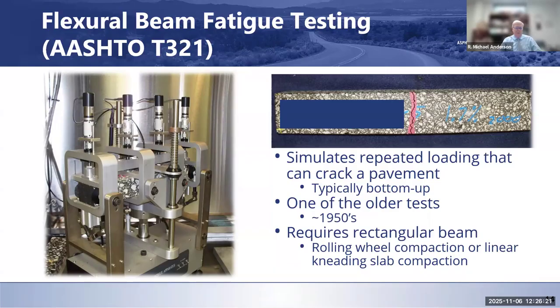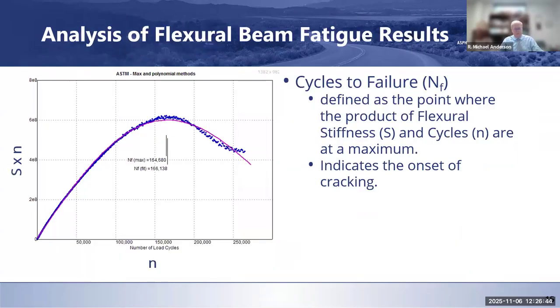So you can see what the beam looks like after it cracks. You develop micro cracks and then ultimately cracks that occur in the specimen. We've just used a red paint pen to highlight what that looks like within the specimen itself. It does require a rectangular beam, so it's not something that we used routinely with our gyratory compactors. We don't make those specimens. Excuse me just a second.